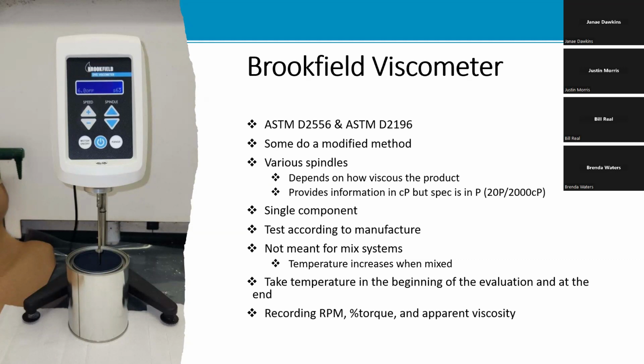So also, when you're testing for viscosity, you're using a single component. You do not want to use a mixed system. One of the reasons why you do not want to use a mixed system is because when the products are mixed together, it's going to be an exothermic reaction. So it's going to heat up and it's going to react very quickly. So you want to test according to what's on the manufacturer's product evaluation. Again, it's not meant for a mixed system because the temperature will increase.